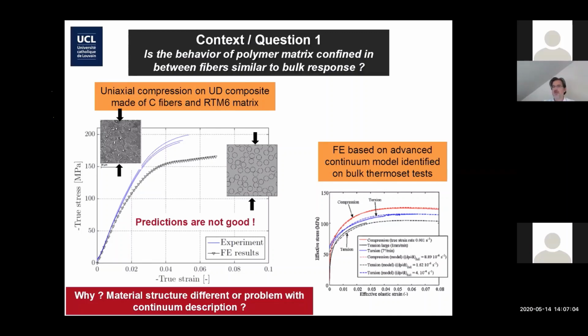So you see on the left side the response true stress, true strain, compression tests that are performed on UD composites. The experiments are the blue lines, and the finite element prediction are the triangles there. So in order to produce this simulation, what we did was we tried to use, and I will come to that during the talk, the best possible continuum mechanics model for the matrix. Very careful, and that's what you see on the right, very careful identification of the constitutive model using compression, tension, torsion models at different rates, etc. And the fitting was excellent, so good.